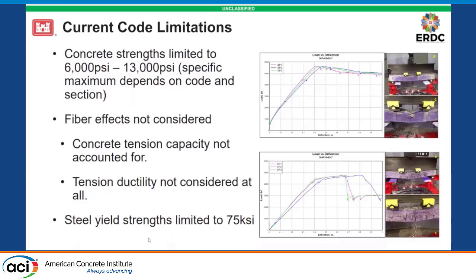So one of the things that is problematic in our current codes is, depending on which code you use, you are limited to between 6,000 and 13,000 PSI. And it doesn't just change with code, it actually changes with section of the code. There are some codes where in one area you can use up to 13 KSI, but in another area you're limited to something much lower. So it's a little bit problematic, and it's also difficult because with ultra-performance concretes, we're seeing values up into the range of 30,000 PSI. I would say for structures and concretes where there's no specialized thermal curing, you're still seeing strengths up to the 18 to 20,000 PSI range.